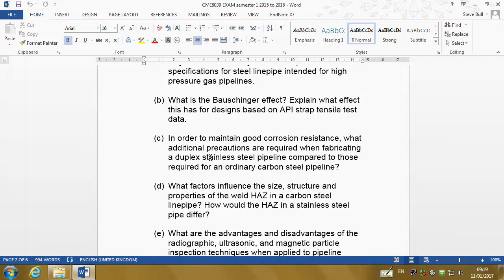What factors influence the size, structure and properties of the weld, heat affected zone in carbon steel, and how would that differ in stainless steel? Now that is a very hard question to answer in 10 marks, because there's lots and lots of things that you could say about that. But to boil it down, a carbon steel heat affected zone is that part where we go through a transition from a ferrite microstructure to an austenite microstructure and back. For stainless steel, it's always austenite, so there is not that phase transition.